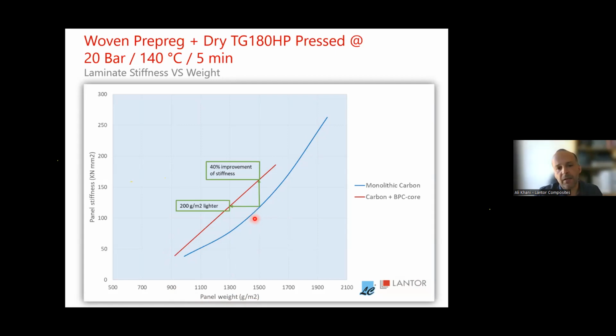So as you can see here, if we have two laminates which have the same weight, like 1500 GSM as the panel weight, you can see that for sandwich option, you have about 40% improvement in the bending stiffness. And on the other hand, if you have the same panel stiffness, you can see that for sandwich laminate, we have about 200 GSM lighter weight.